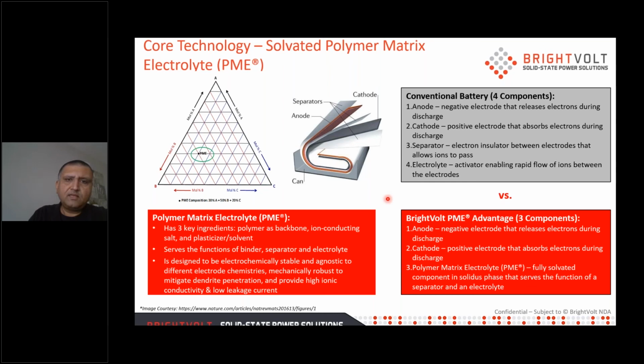And so if you look at the individual constituents of electrolyte and separator, as we all know, the liquid electrolyte is usually a mix of one or more lithium-ion conducting salts that are dissolved in an organic solvent. And then the separator is usually a PP type membrane. And so in a nutshell, what the polymer matrix electrolyte, or the PME, comprises of is a backbone polymer combined together with one or more lithium-ion conducting salts and a plasticizer or solvent, all in a single homogeneous and uniform state.